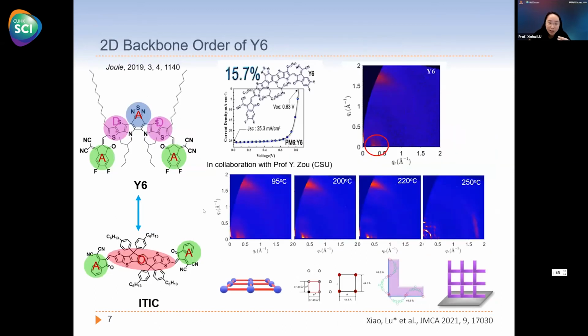So then we go into the next generation, this Y6. This is another milestone molecule synthesized by Yingping Zou in Central South University, which pushed the efficiency of organic cells over 15% in recent years. So compared to the ITIC family, Y6 has this L-shaped backbone. So whether this Y6 can also have backbone order in the in-plane direction. Okay, so for Y6, in the GIWAXS pattern, the crystallinity is much lower, so we cannot guess what the packing structure is just by these blurry peaks.